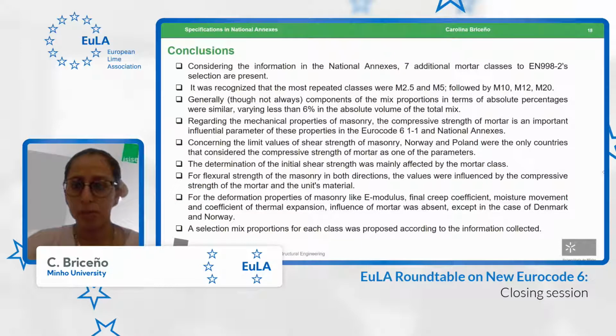Finally, for the conclusions, considering the information in national annexes, we see that there are 7 additional mortar classes to those available in the standard EN 998-2. Also, it was recognized that the most repeated classes were mortar class 2.5 and 5, followed by mortar class 10, 12, and 20. In general, but not always, the components of the mix proportions in terms of absolute percentage were similar, varying less than 6% in the absolute volume of the total mix.